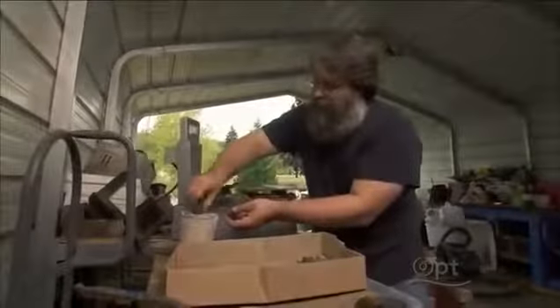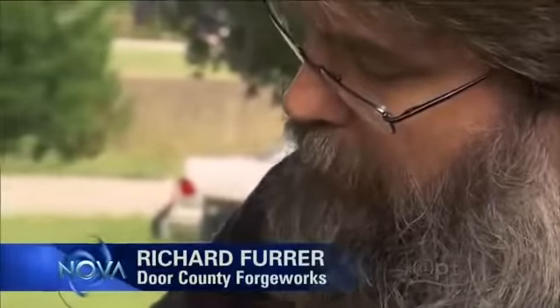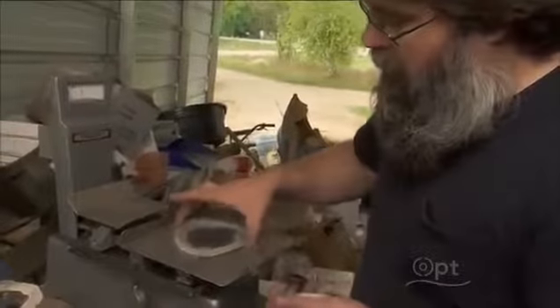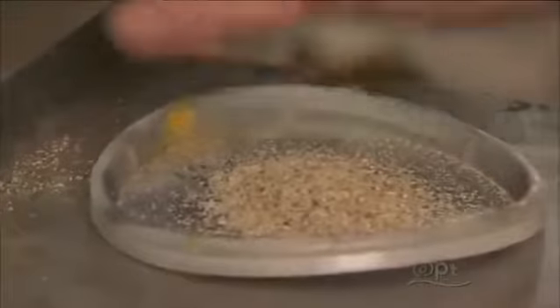Starting with raw iron, Rick begins the process of making crucible steel — the first of many steps on the way to a finished sword. This charcoal will be the carbon source, absorbed into the steel. Sand and bottle glass will melt, chemically bond with the waste slag, and help float them away, leaving clean metal so the carbon can be absorbed.